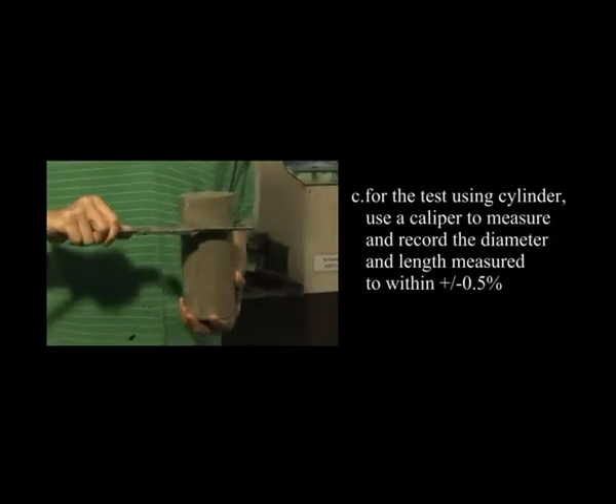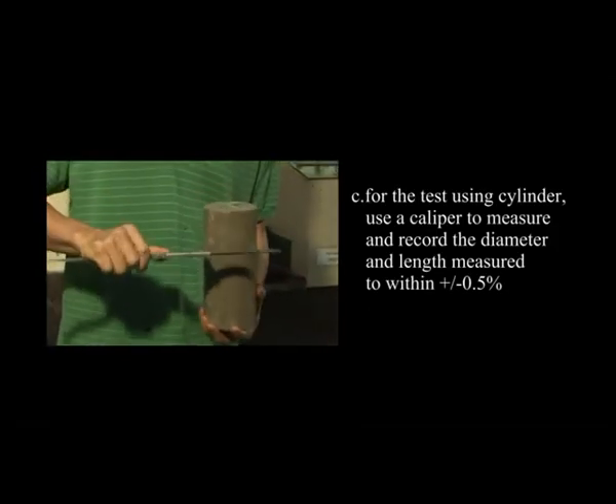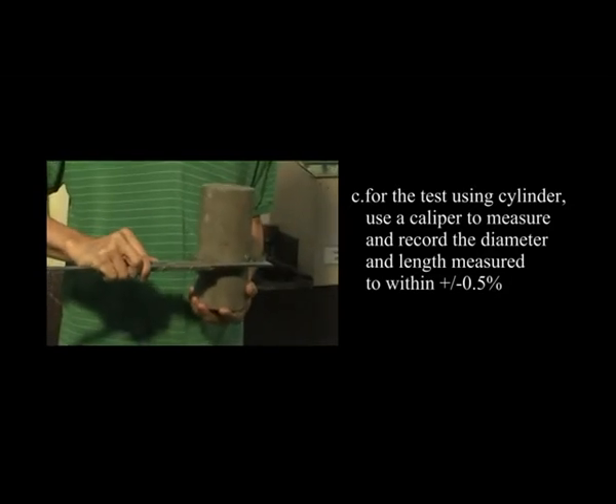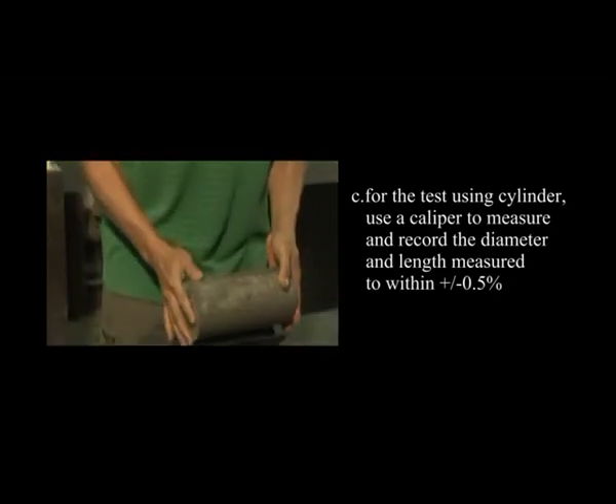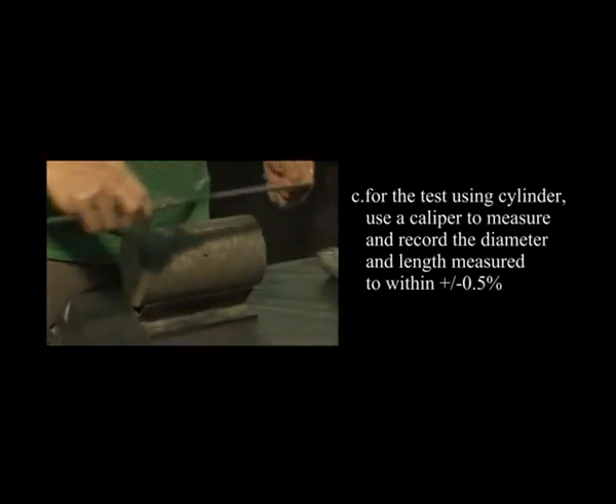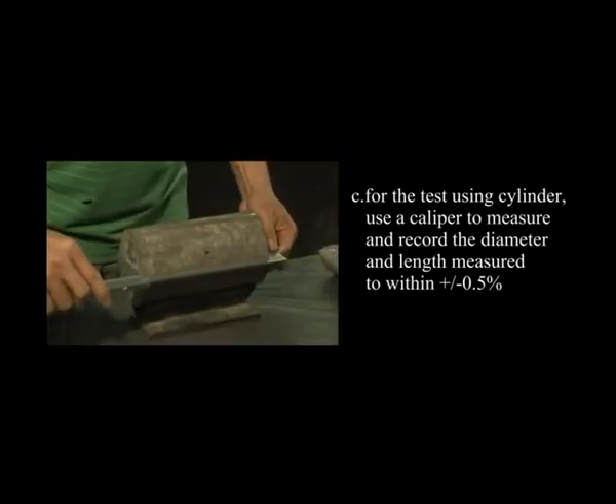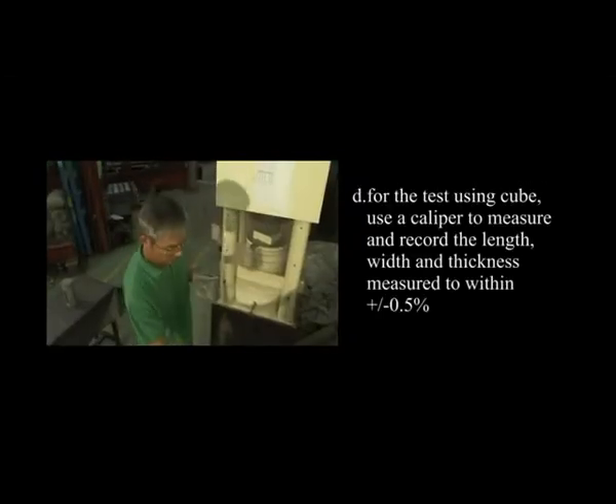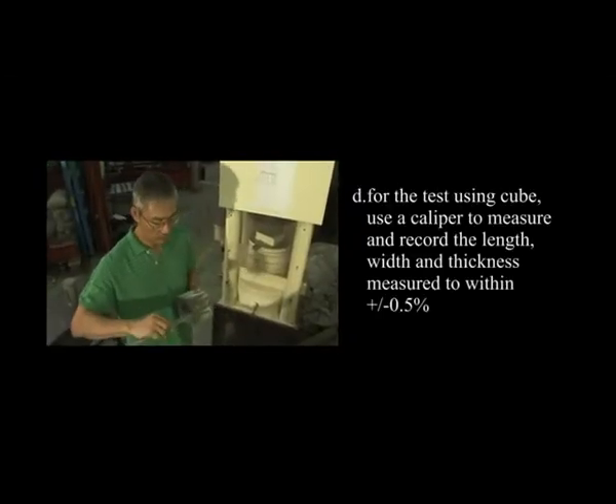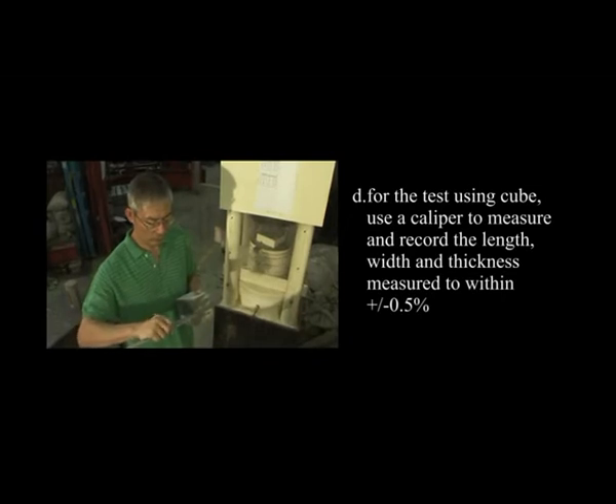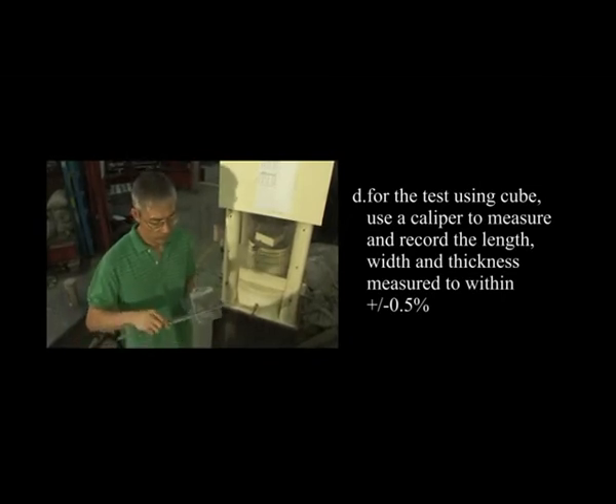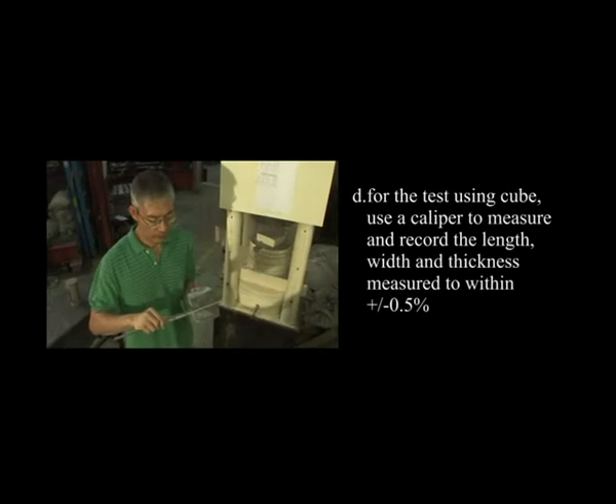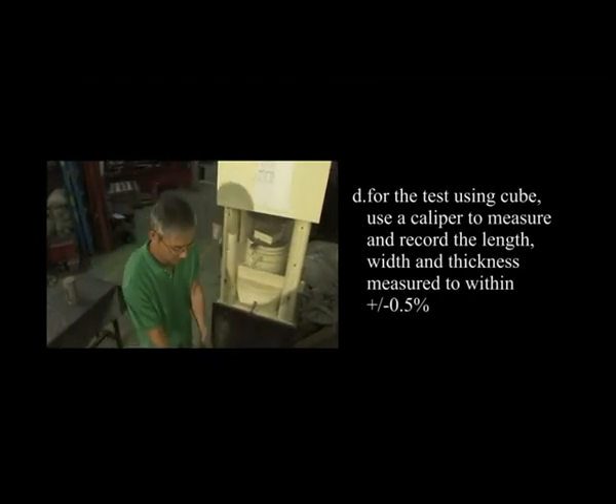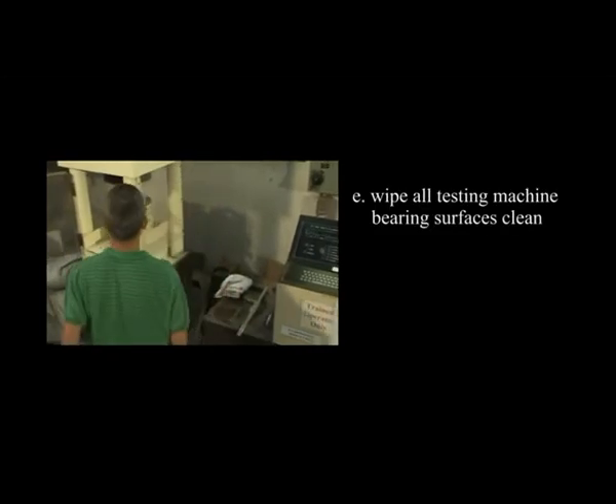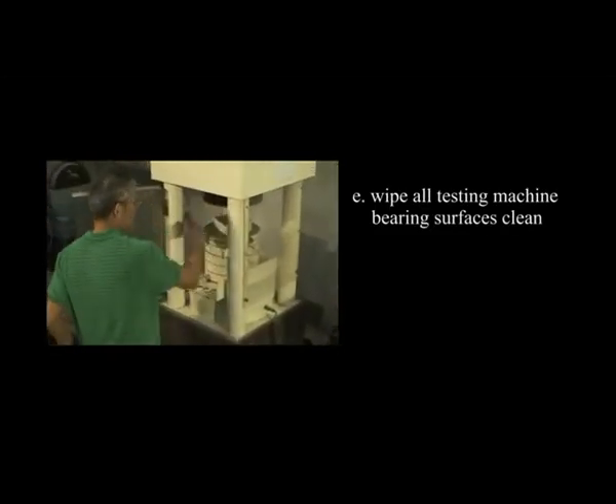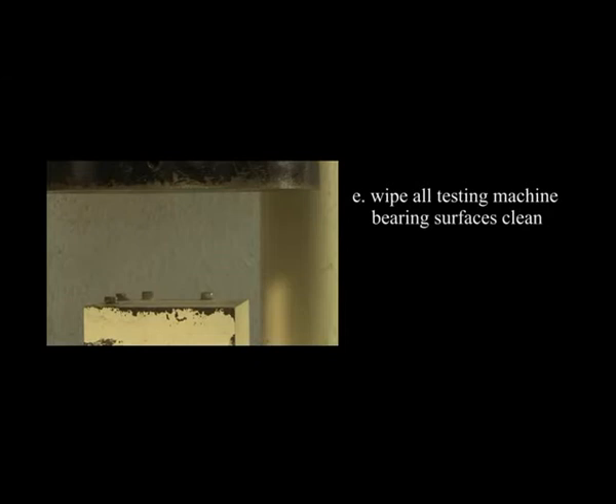C. For the test using cylinder, use a caliper to measure and record the diameter and length measured to within plus or minus 0.5%. D. For the test using cube, use a caliper to measure and record the length, width, and thickness measured to within plus or minus 0.5%. E. Wipe all testing machine bearing surfaces clean.